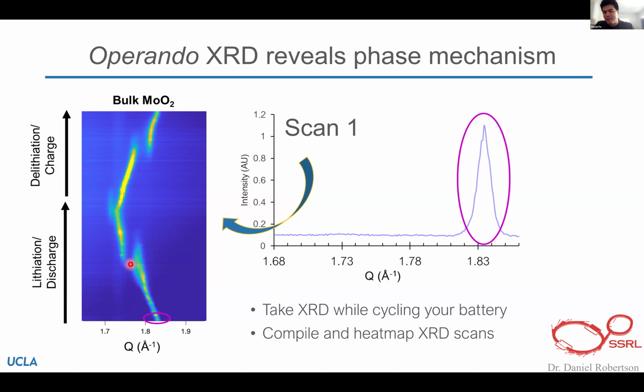And then we reach this gap here for bulk MoO2, and that is what I was talking about earlier. When you reach a solubility limit of lithium, we can no longer accommodate lithium. So instead of continually expanding our material into a larger size, we see the nucleation and growth of a new phase here that is able to accept more lithium. And then that continues to grow, and then it continues down.